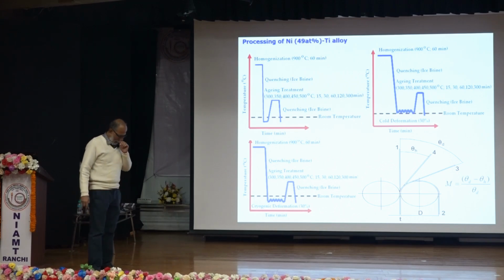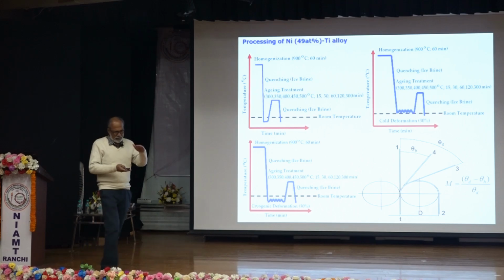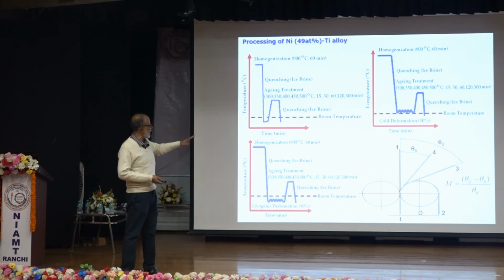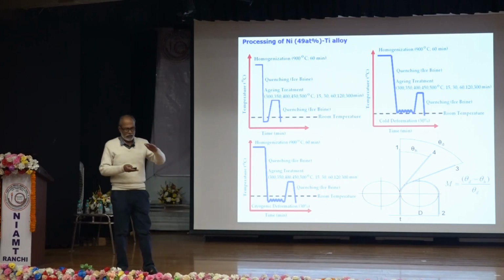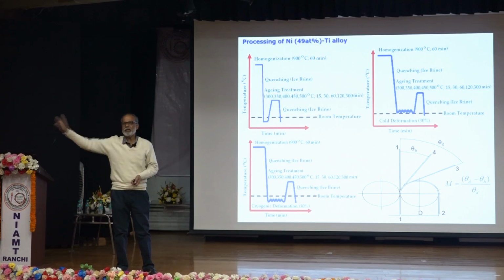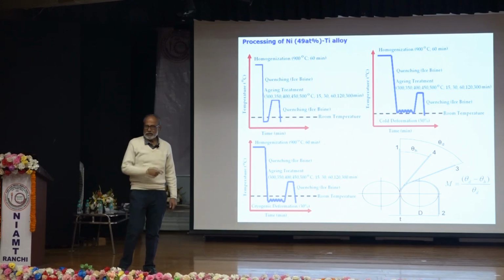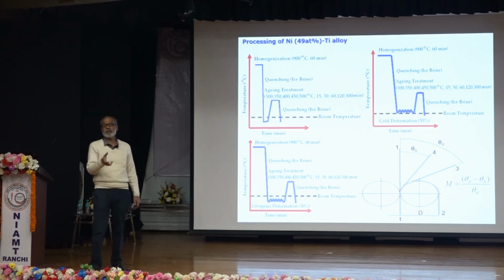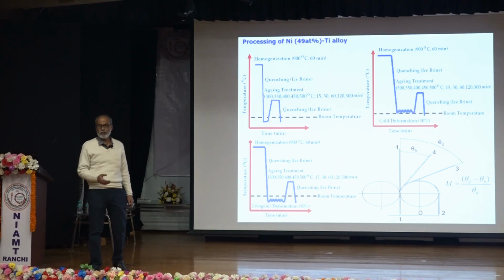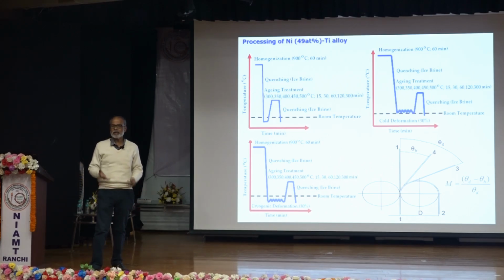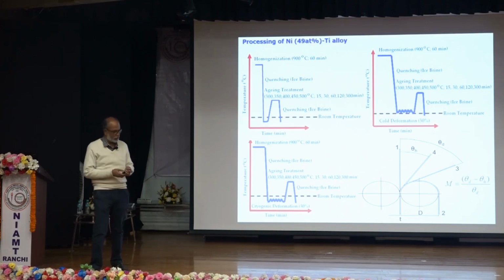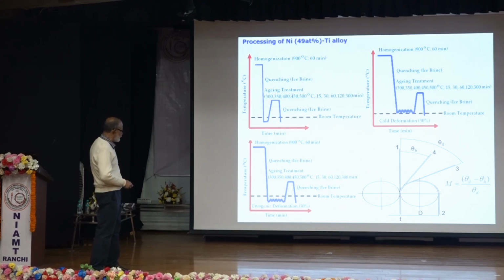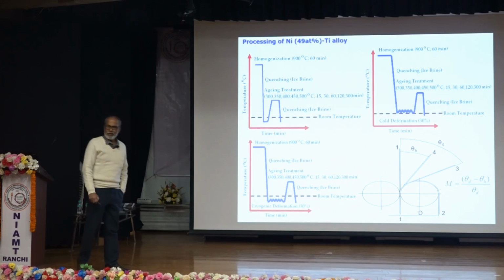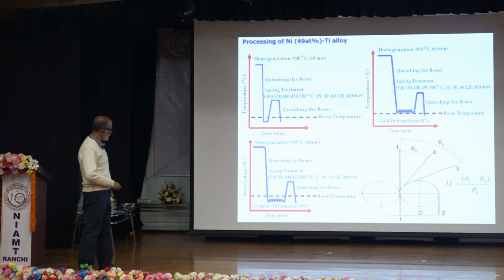Why? Because the difference between the temperature and Ms temperature is the driving force. I'll have some equation. It is the Koistinen and Marburger equation. The equation is simply volume fraction of martensite is 1 minus exponential of beta into (Ms minus T). So Ms minus T, that is the temperature difference, is the driving force. Here we have a very low temperature gap, it is only 63 or 64 to room temperature, right? So very often people come across retained austenite in the system. Instead of fully martensitic, they get a martensite-austenite mixture. So that's why we quenched it at a very low, cryogenic temperature, so that there can be very high driving force. We deformed it there and we conducted aging.